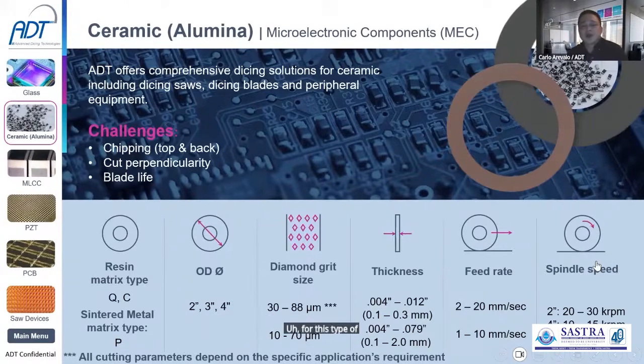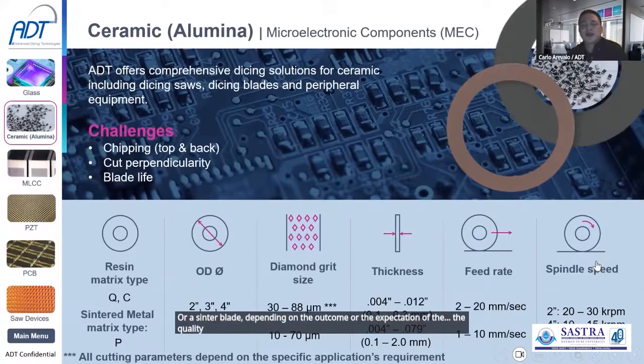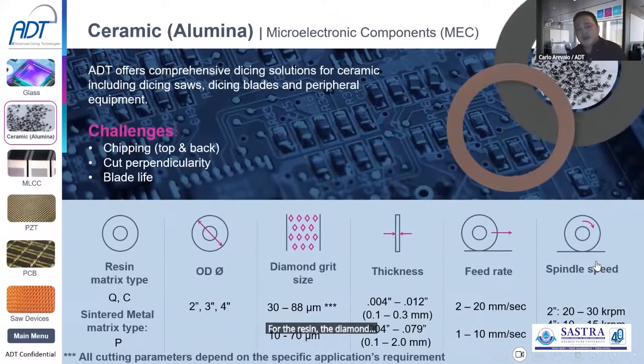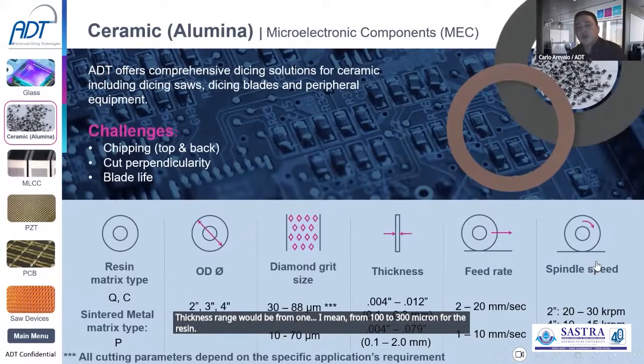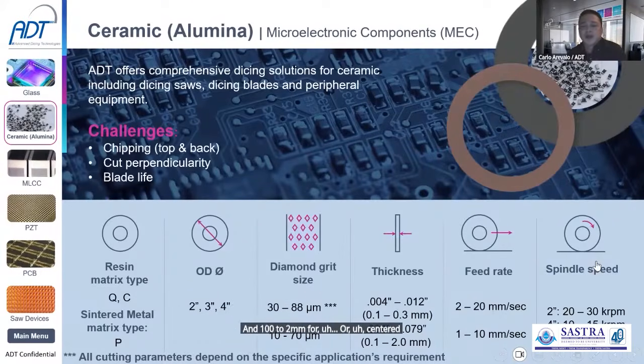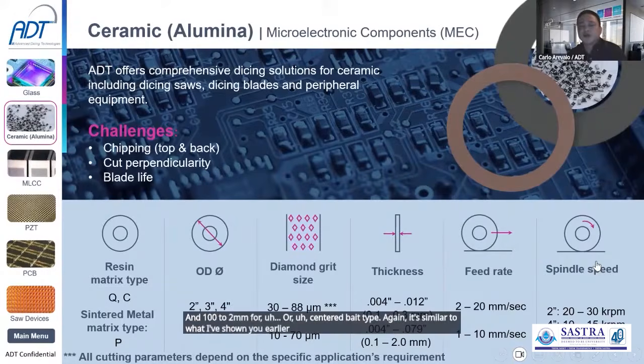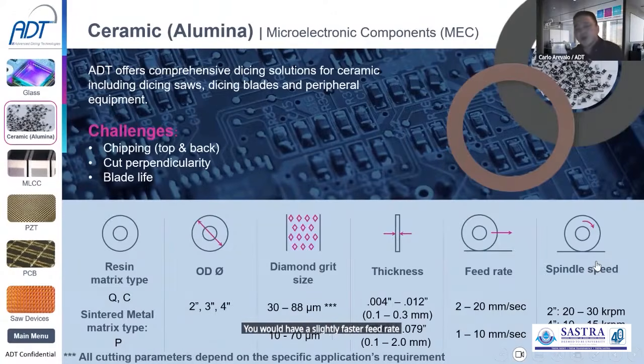For this type of material, we can either do it with a resin or a sintered blade, depending on the outcome or the expectation of the quality. The OD size can be 2, 3, or 4 inches. For the resin, the diamond grit range can be from 30 to 88 micron. If you're using a sintered, it can be from 10 to 70. Thickness range would be from 100 to 300 micron for the resin, and 100 micron to 2 mm for the sintered blade type. Again, it's similar to what I've shown you earlier. For the cutting feed rate, you would have a slightly faster feed rate using a resin blade, but still relatively low, considering the speed can only go as much as 20 mm per second. So spindle speed, again, is relative to the blade size that you are using and the machine that you're going to dice it with.